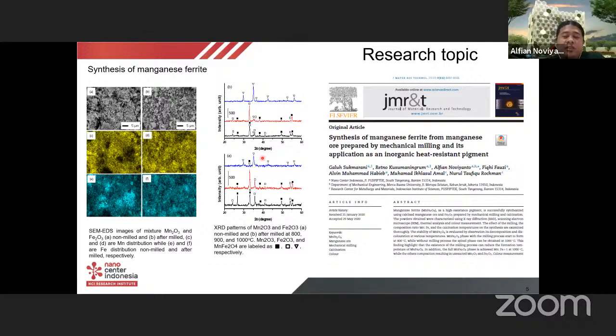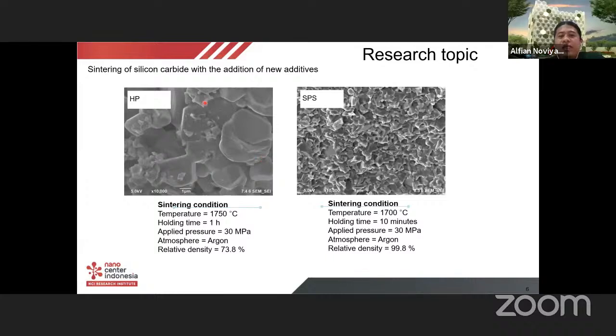This is another result. We sintered silicon carbide with the addition of a new additive. We used two kinds of furnace, hot pressing and spark plasma sintering. Using spark plasma sintering, we can obtain very dense structures and a very fine grain size compared to the hot press. It should be mentioned that the temperature is lower than hot pressing, only 1700 degrees C versus 1750 degrees C, and the time is very fast: only 10 minutes, whereas hot pressing needs 1 hour.